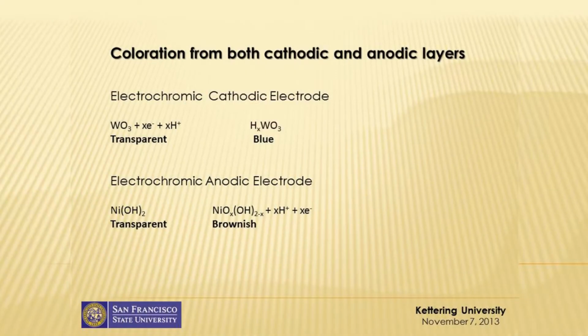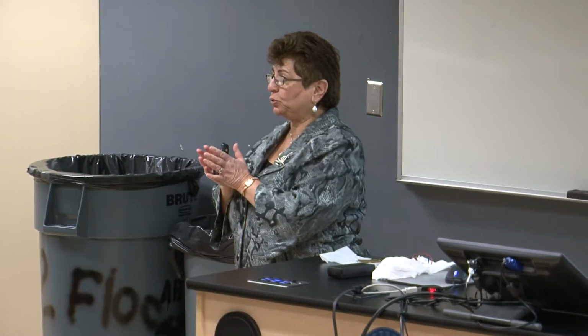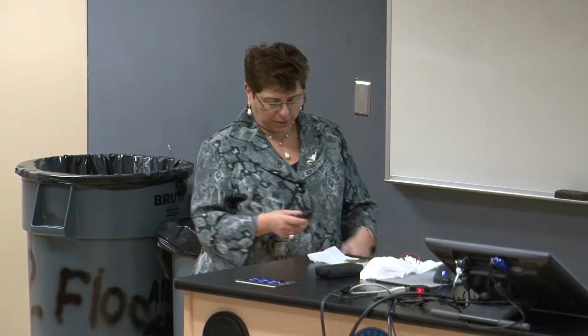Coloration from both cathodic and anodic layers. The first reaction, electrochromic, occurs in the electrochromic cathodic electrode. Tungsten oxide is transparent, but when it is reduced by proton insertion, it becomes blue. The electrochromic anodic electrode reaction is that in this sample I use nickel hydroxide. Nickel hydroxide is transparent, but when it is oxidized, it becomes a brownish color. So if you use the blue and brownish color together, you obtain a more natural color than the dark blue color. It becomes more natural.